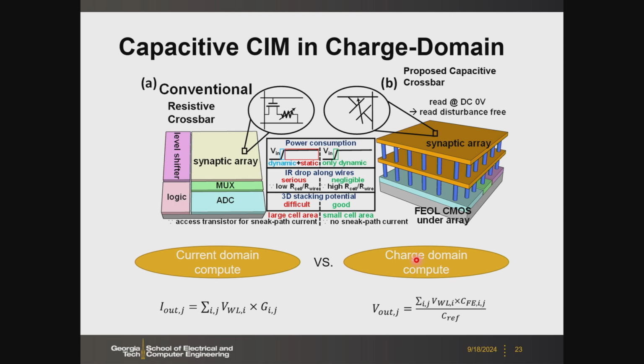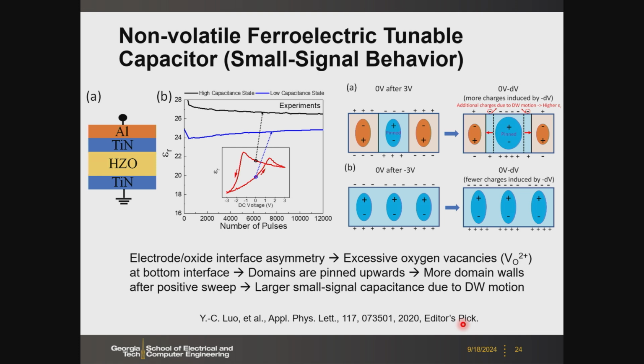So here we do the charge transfer process, and then we will show you the output voltage is proportional to the input voltage multiplied by the capacitance of this crossbar array, modulated by the reference cap at the edge of the array. So this is our vision. And then we started from this simple MFM cap. So this is nothing special here, titanium nitride, HZO, and titanium nitride.